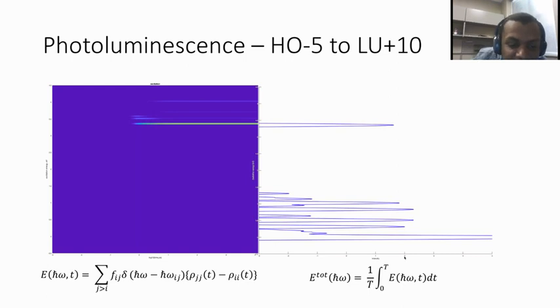So we excited HOMO -5 to LUMO +10. So now we have a hole in the valence band, and a hole in the conduction band, and an electron roaming around. So they're going to approach the band gap, or HOMO-LUMO. So they're losing energy as they approach that, most likely to heat. Not necessarily. The phonons? Yes, phonons. So when they actually reach the band gap, they have less energy. There's less of an energy difference than what we started with. So instead of emitting at 4.9, we get an emission at 3.3 eV.